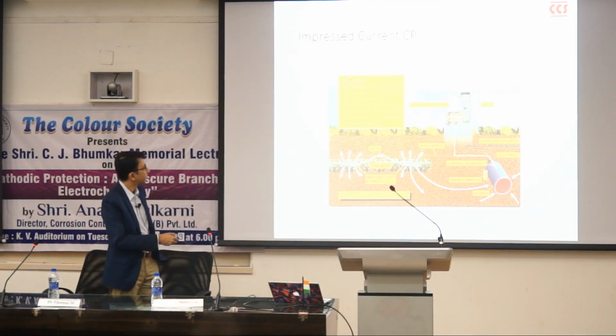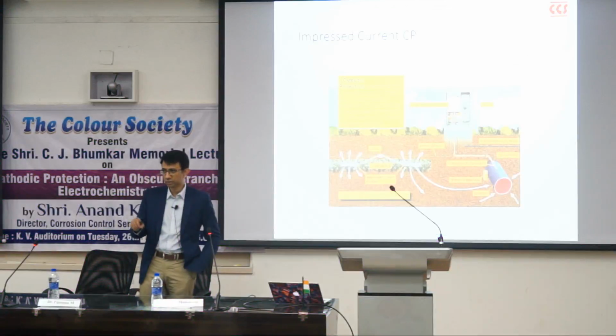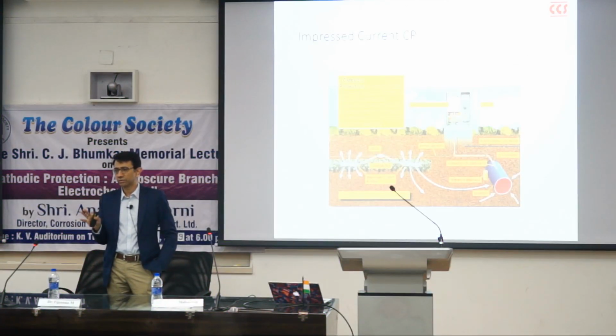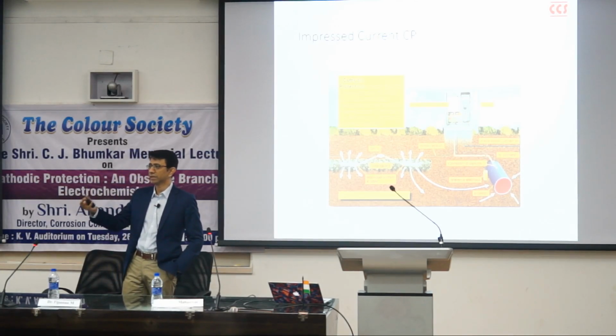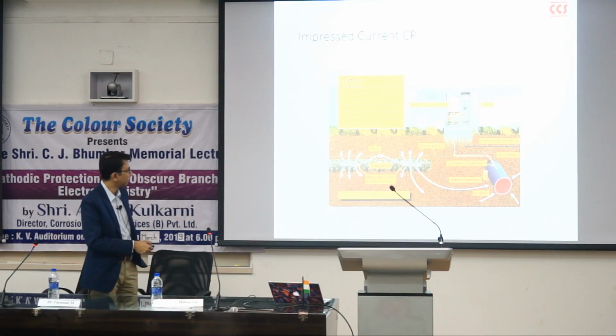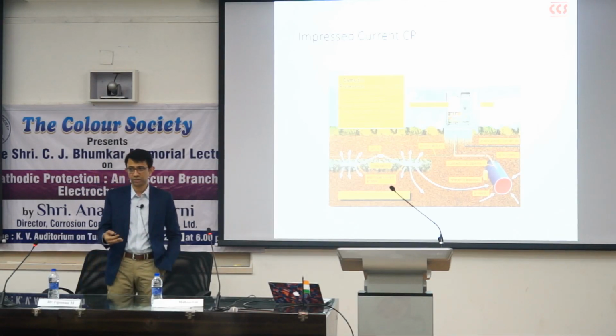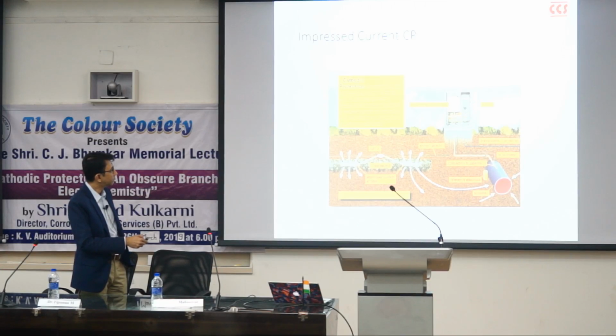So this is a slide for an impressed current CP system. This is an external DC power source, transformer rectifier, and these are what are called impressed current anodes. The impressed current anodes are intrinsically different from the galvanic anodes that we saw earlier. So we talked about magnesium and zinc and aluminium, but these impressed current anodes are quite different. They're typically made of inert materials, materials which do not get consumed easily. And we find that these anodes are connected to the positive terminal of the TR, the negative is connected to the pipe. This is a reference electrode for monitoring of the potentials.